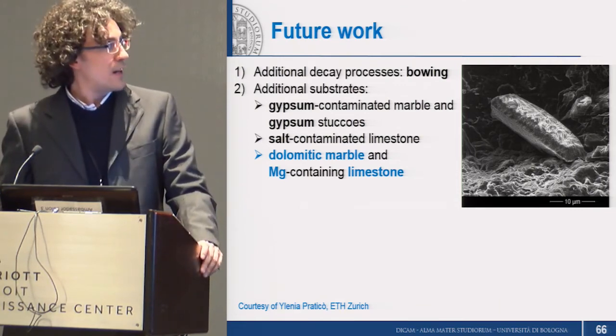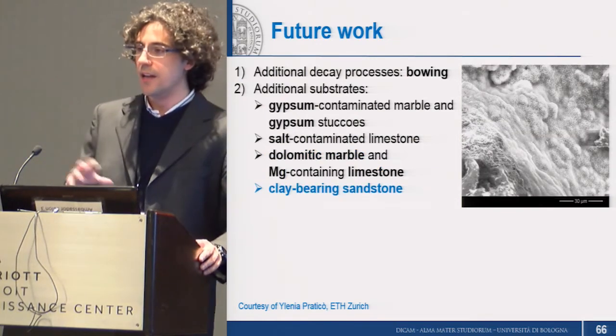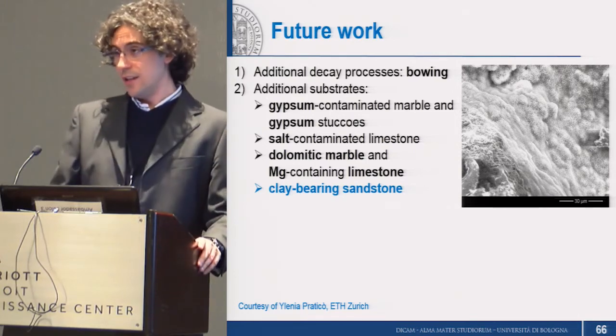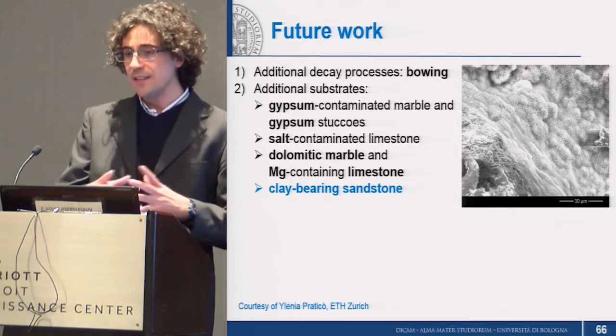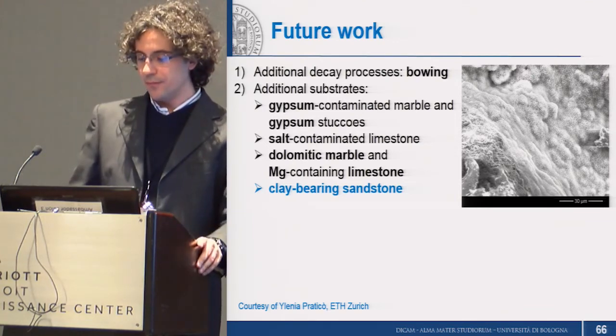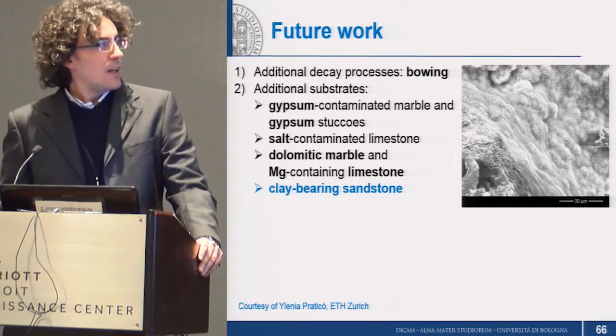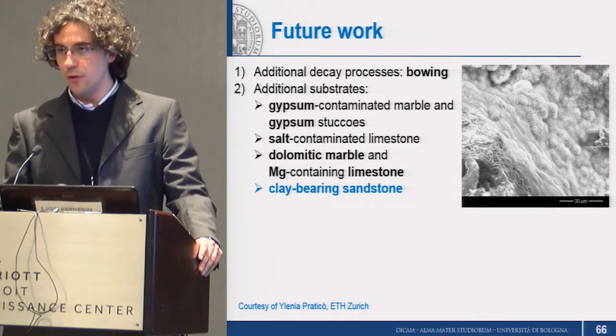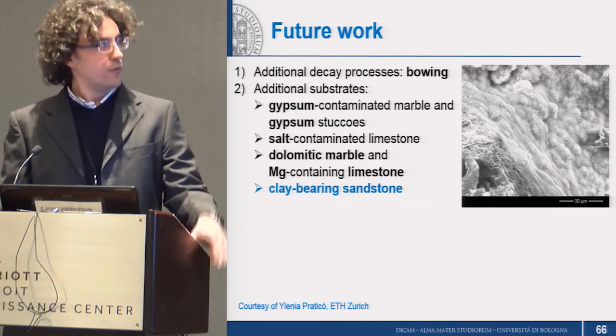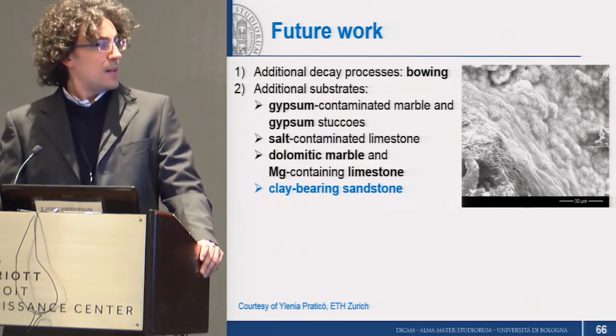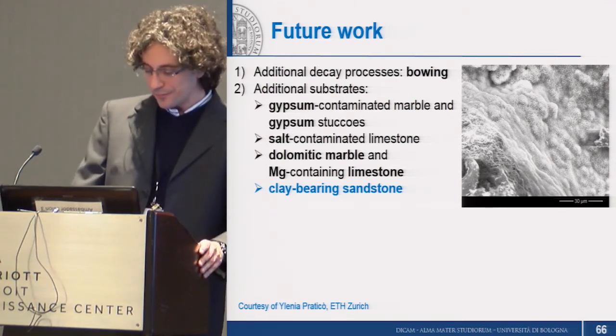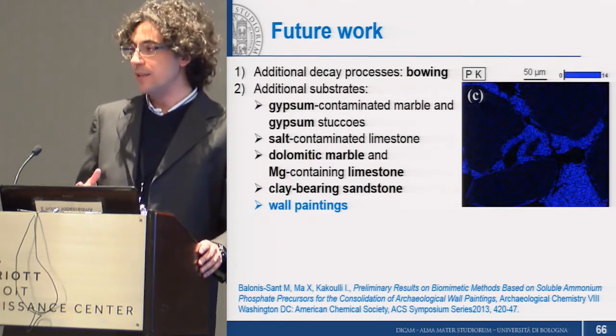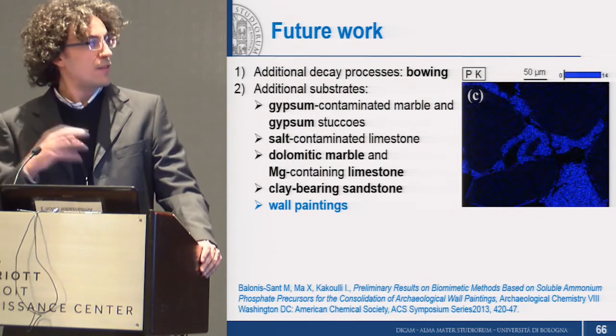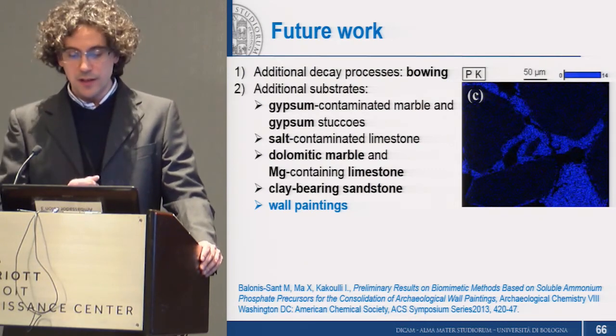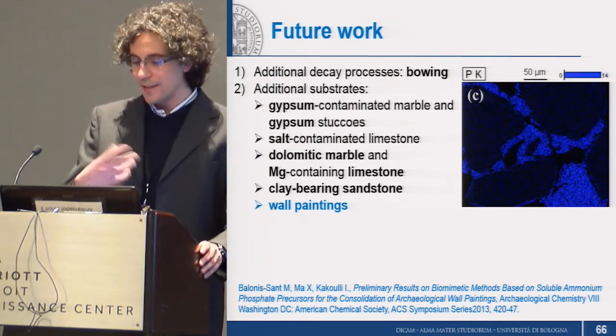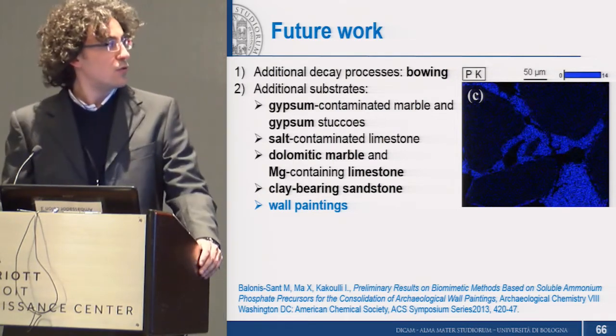People at ETH in Zurich are also studying the effectiveness of this treatment on clay-bearing sandstones, which is a very important and tricky substrate because these clays swell, so increase in volume when they are in contact with water. And again, traditional consolidants are unable to make these stones resistant to this kind of weathering phenomenon. So hopefully our treatment will be able to do so. Then people at UCLA are studying the effectiveness of using this treatment also for wall paintings that have basically the same type of matrix, a calcitic matrix, but also the presence of carbonate or silicate aggregates, and also oxides that were used as pigments, so that's an additional factor to take into account.